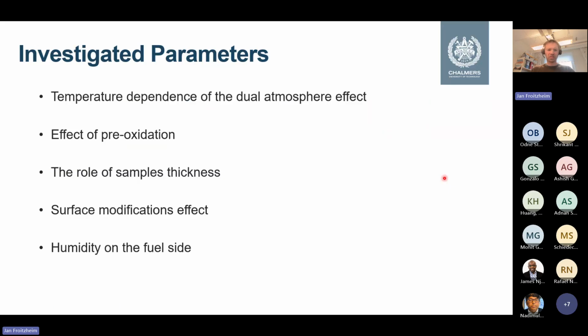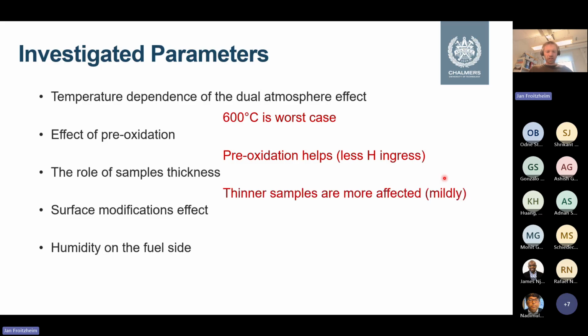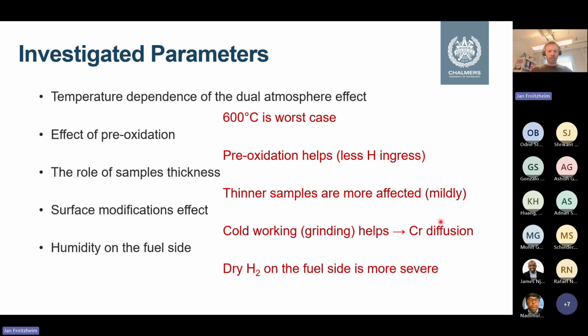To summarize: 600 degrees C is the worst case. Pre-oxidation helps, gives us less hydrogen ingress. Thinner samples are more affected, but the effect is not super strong. Cold working, for example grinding, helps, giving us higher chromium diffusion. And the humidity on the fuel side matters - if we have dry hydrogen on the fuel side, that is more severe.